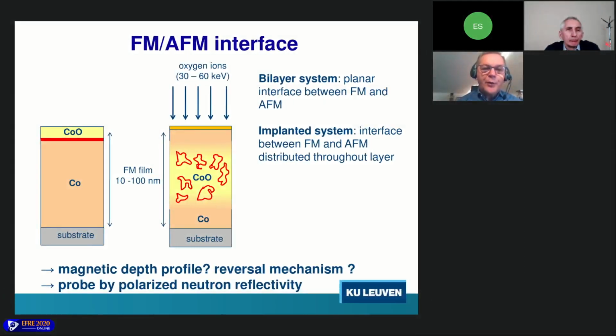Okay, now the question that remains is the following. So instead of having a single interface between cobalt oxide and cobalt in the bilayer, we now have a distribution of cobalt oxide throughout the entire thickness of the cobalt layer. And then the question that arises is, what does this look like magnetically? Can we establish a magnetic depth profile, and can we say something about the way that magnetization is reversing in such a system? And so a good way to probe that is to use polarized neutron reflectivity.